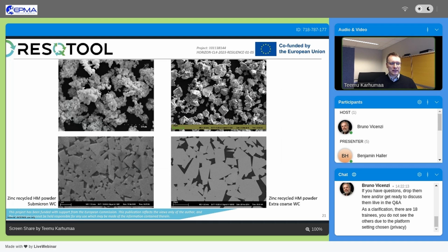So in this case, this is submicron material consisting of tungsten carbide grains and cobalt here, and this powder can be fed then directly to the attritor milling step in the RTP production for the hard metal supply chain, and can replace virgin tungsten carbide and cobalt. If you look at the little bit coarser tungsten carbide grain size powder, the powder is not that much agglomerated after recycling, but there are more single tungsten carbide grains and then cobalt here and there.